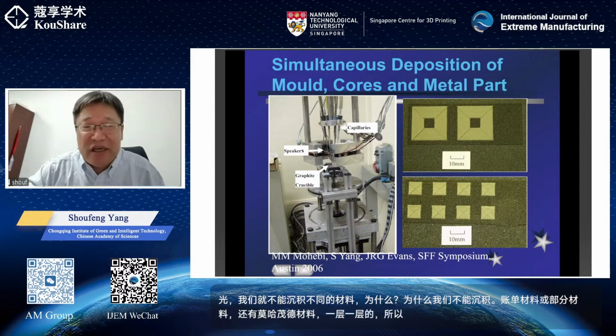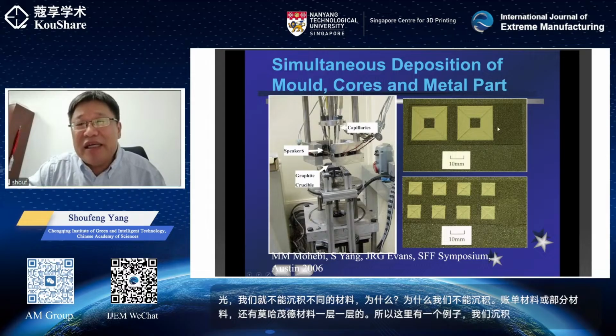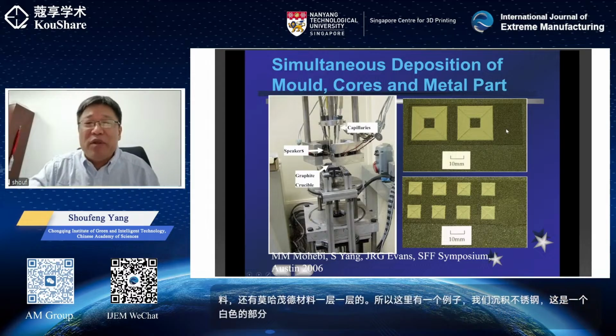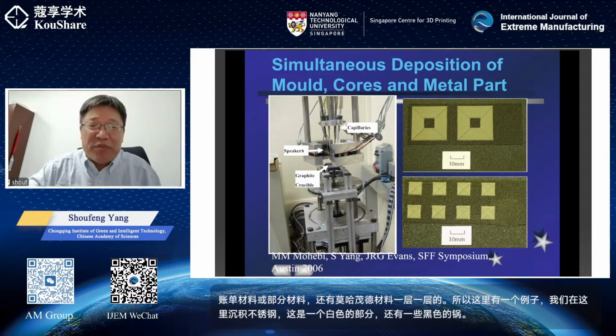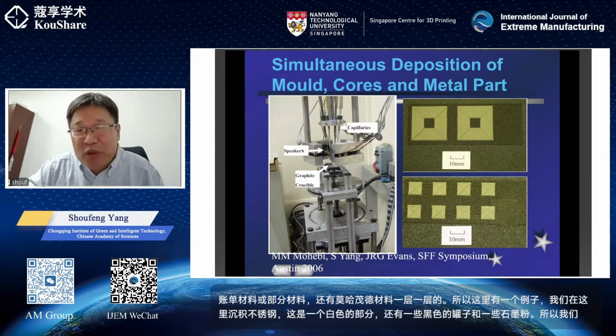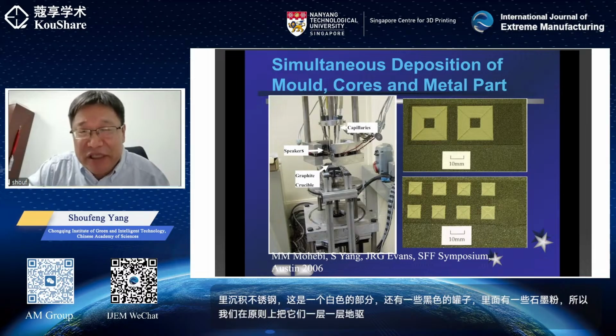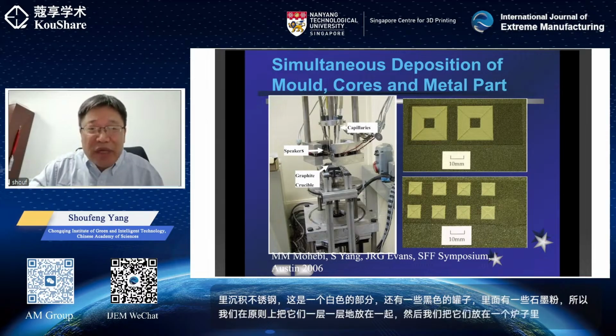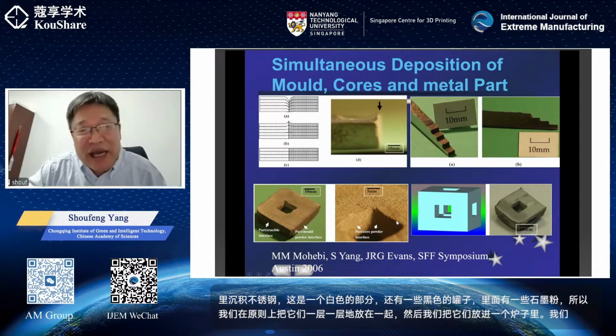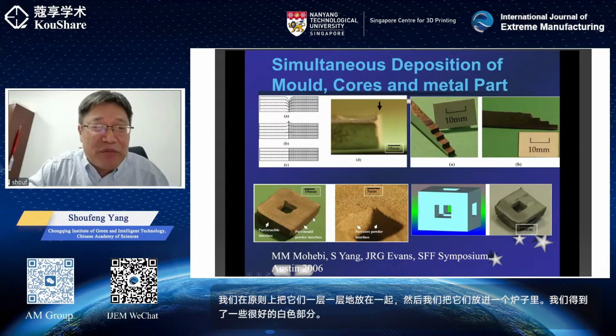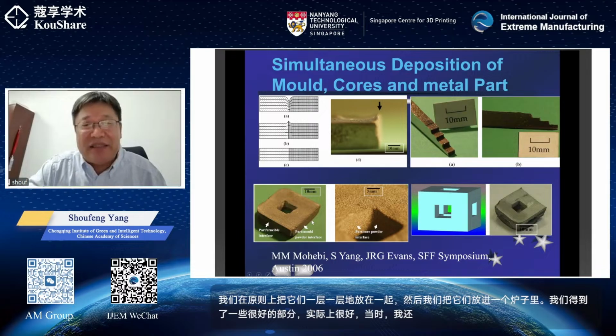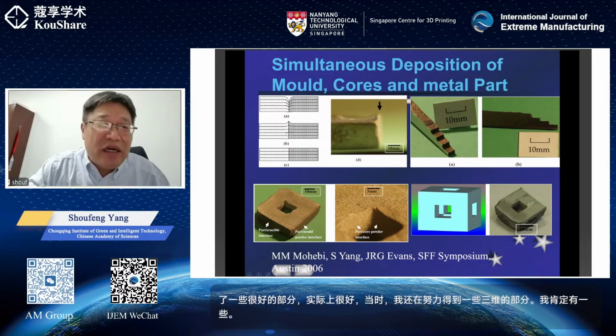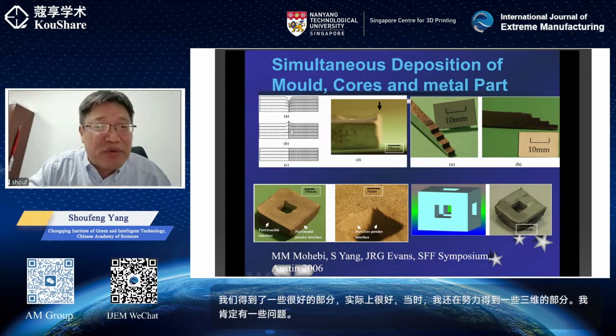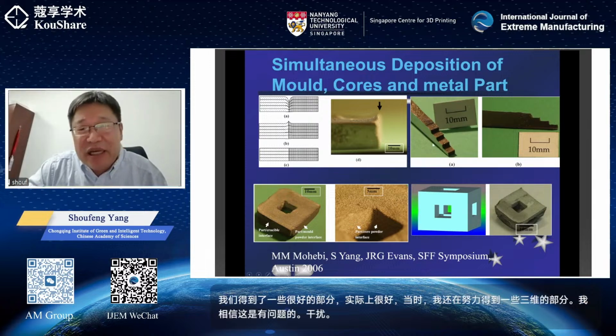So here is an example. We deposit stainless steel, which is the white part here, and also some black part with some graphite powder. So we deposit them together, layer by layer in a crucible. Then after that, we put it in a furnace, and we got some nice part. Well, quite not that nice actually at that time, but we still struggled to get some three-dimensional parts. And sure, there's some problem with this interface, and we built some staircase.